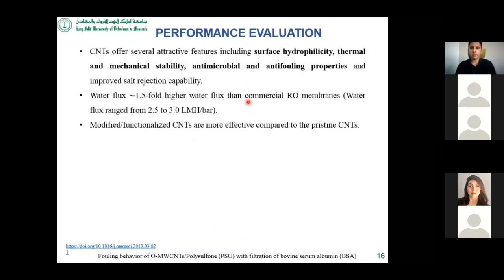So what are basically the advantages of adding the CNT? As I mentioned earlier, it increases the hydrophilicity, so you can expect high flux. It increases the thermal and mechanical stability that is required for some application. And also it improves the antibacterial and anti-fouling characteristic of the membrane, as well as the salt rejection efficiency. If you compare this with the commercial RO membrane, the flux is almost 1.5 times higher than the commercial membrane. And this is a very big statement.